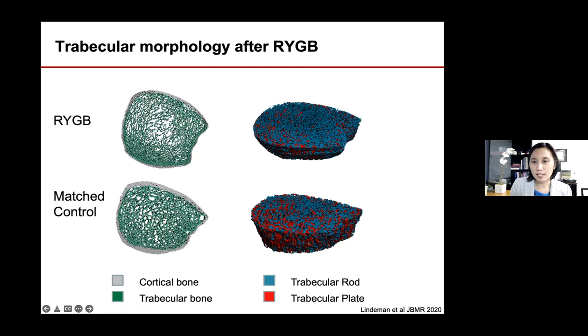And in this column here, you can see the 3D rendering that also includes information about trabecular rods and plates. And in addition to the overall increase in cortical porosity and decrease in trabecular density and trabecular number that are visible just on a visual representation of the gastric bypass and the matched controls, you can also see that there's a preferential loss of the trabecular plates, shown here in the red coloring, in the gastric bypass patients.